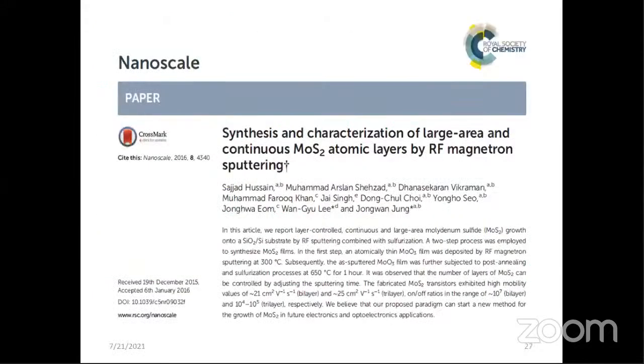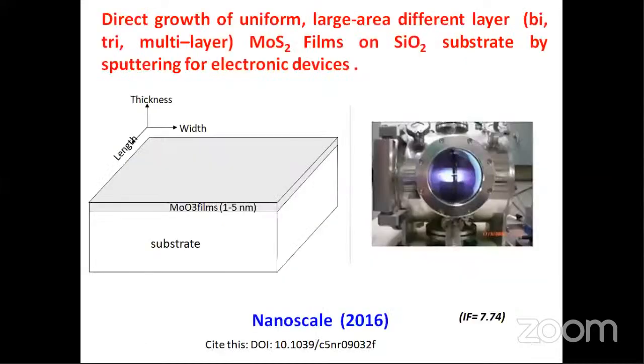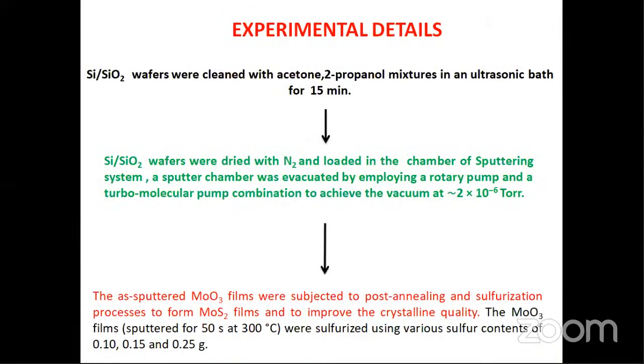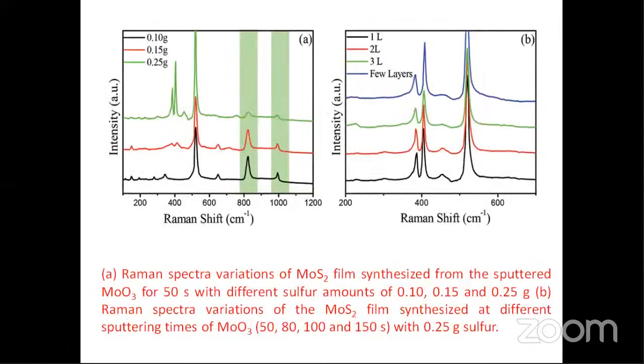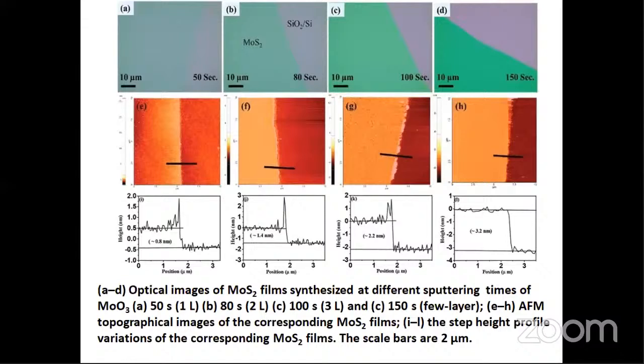In the CVD system, we take two steps. First we deposited MoO3 and then we sulfurized it by the CVD method. Then we found this system gives very good quality samples, and the amount of sulfur is very important here. We found very good quality in a very controlled manner over a very large area.